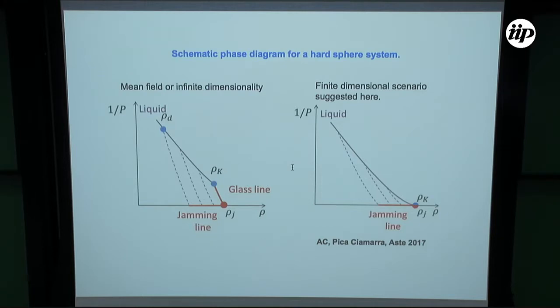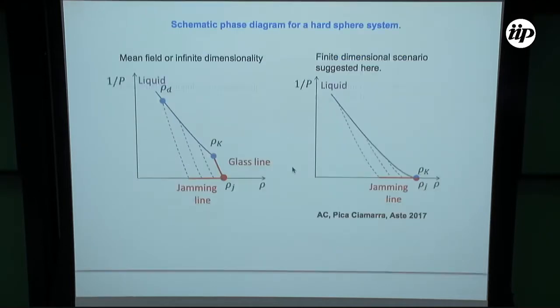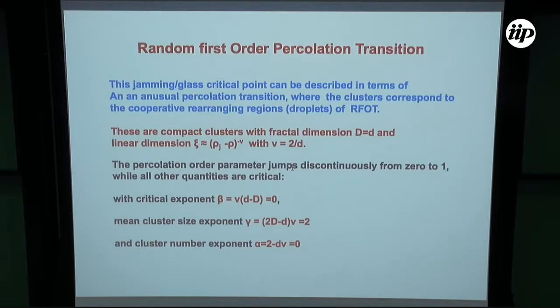So, schematically, this is the phase diagram in mean field or infinite dimensionality. And what we suggest here is that the phase diagram should have this equilibrium line, which ends at density rho k, which coincides with rho j. So the end of this line is a point which is both the ideal glass transition and the jamming transition.